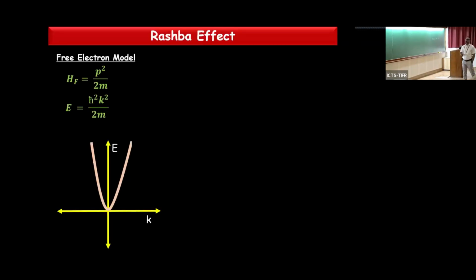A possible non-trivial spin texture in momentum space is a Rashba system. And what is that Rashba system? For a free electron, the Hamiltonian is p squared by 2m, and the energy is proportional to k squared, a simple parabola. Now if you think of an electron moving with a relativistic velocity under the application of an electric field, then in the rest frame of the electron this electric field is converted into a magnetic field because of the Lorentz transformation, and now your spin is quantized along this direction.